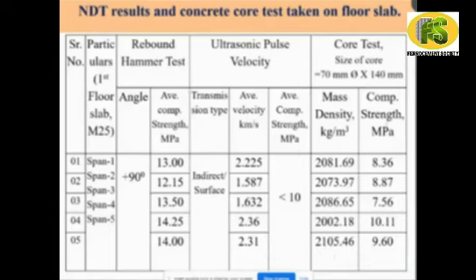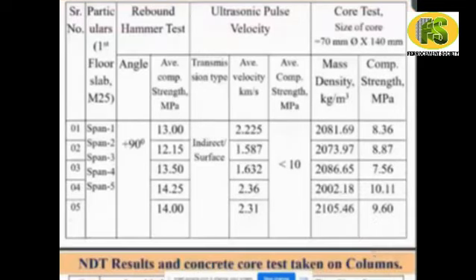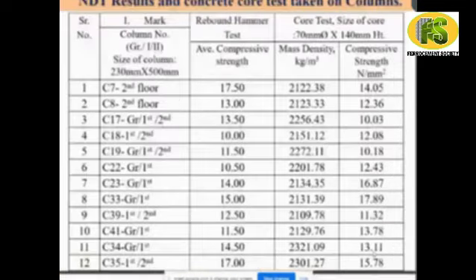And that's why the compressive strength of the core is 8.36, 8.87, 10.11 and 9.60, which is very low. We can say that it is less than 50%, because the grade of the concrete is M25. And here it is observed that after testing the core, the compressive strength is just 10 MPa or less than that. These are the NDT results for the column.